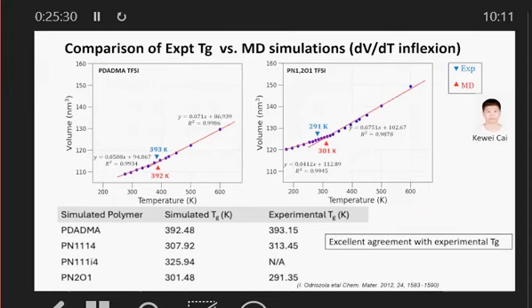So in the MD simulation, we can do this. We can measure the volume as a function of temperature, and we can then take the gradients, and we can see where the Tg is. Interesting for the polyDADMA TFSI, which is notoriously hard to measure Tg in a DSC. It's also quite hard to measure it even in the volume change. It's there, but it's very subtle, and that must be something to do with the material itself not having a massive change at Tg, and that's something for another story for another day.